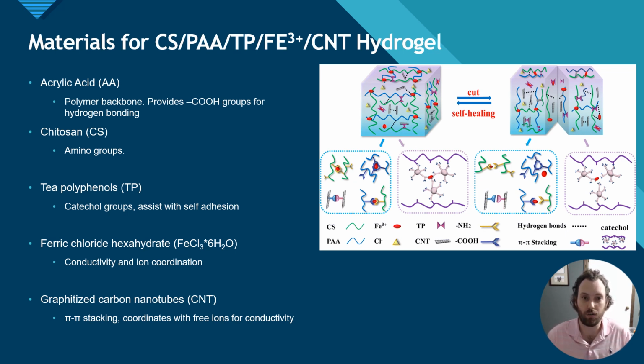Tea polyphenols add the catechol group, or 1,2-dihydroxybenzene. This plethora of OH groups gives us the capability to self-adhere to substrates due to these OH groups. It also has marginal benefits as an antioxidant and possible sterile agent. Ferric chloride hexahydrate was added to our polymer in order to induce free ions. This will elicit the conductivity of our ion, and also, as I mentioned before, will give us the ability to form coordination alongside our carboxylic groups and our amino groups. Lastly, to further modulate the modulus, carbon nanotubes were added to our mixture as well.